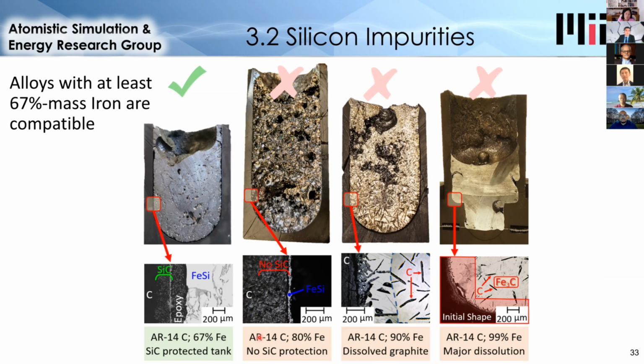When we use more than 67%, for example, 80 or 90%, we find that a silicon carbide layer does not form, and in fact, an iron silicide, FeSi, forms at the interface, and a lot of the carbon wall was dissolved. At 90%, we could observe a lot of carbon in the liquid itself that precipitates out on cooling. And finally, if pure iron was used, we see that the tank wall actually dissolves up until the point that the liquid is saturated with iron. And so this was very important because it showed that we could actually dilute the silicon with 2/3 iron.